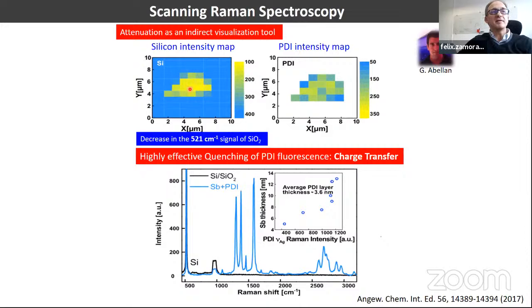And then we treat this layer with the perylene diimide (PDI) molecule. And what we observed was that we have Raman signals corresponding to this molecule, perylendiamine, on top of the initial layer. But this was also interesting because initially this molecule is a strongly fluorescent molecule. So in order to be able to see these Raman signals of the molecule, you have to assume that you have a kind of charge transfer between the molecule and the antimony, quenching this strong fluorescence.